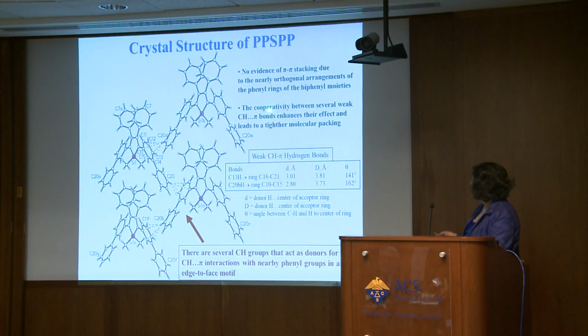And we noticed that there is a cooperative interaction between carbon-hydrogen and pi bond, which enhances the packing of the molecules. So it's fairly tight packing. We see that there are several CH groups that act as donors for this CH-pi interaction with the nearby phenyl group in an edge-to-face position.